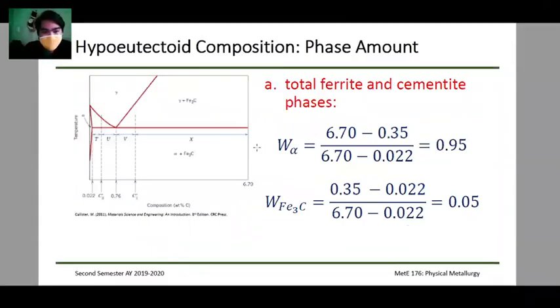Okay, so the way we compute that is, since we're using the tie line, our tie line is from here to here. If we want to measure the alpha phase, then it's just 6.7 minus 0.35, from here, divided by 6.7 minus 0.022, because this is the total length of the tie line. Then the amount of alpha it produces is this lever. From here to here is the alpha phase. Okay? So you should get a value of 95%.